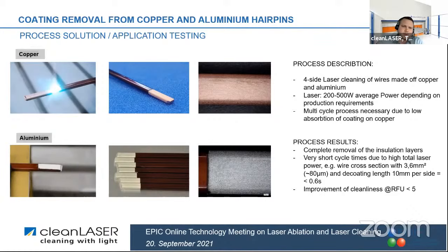We normally use lasers with an average power between 200 and 500 watts, which allows removal of this coating without damaging or modifying the blank material. This process is not possible to treat in only one pass. This means we have the challenge in the setup or in the parameter finding that you have to do several passes over this area to have a very clean surface in good quality. The result, the need, is to have a complete removal of this coating and then very good cleanliness. And therefore we have different measuring systems to use.